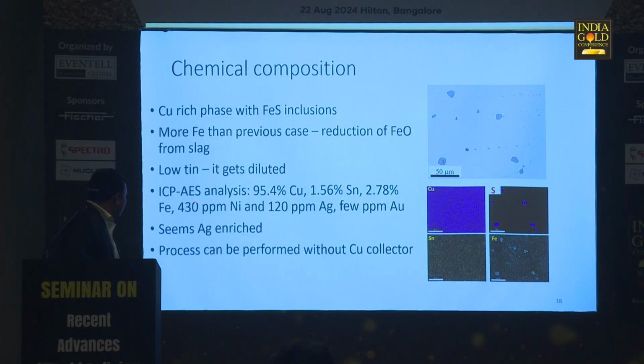Things get diluted, so you have only a few ppm of gold, but we did not find any major difference in composition if you do the mass balance, in either case, whether you had physically separated or not, except for silver, where you can see that even after diluting 10 times, there is 120 ppm silver in this case compared to 700 ppm in the previous case.